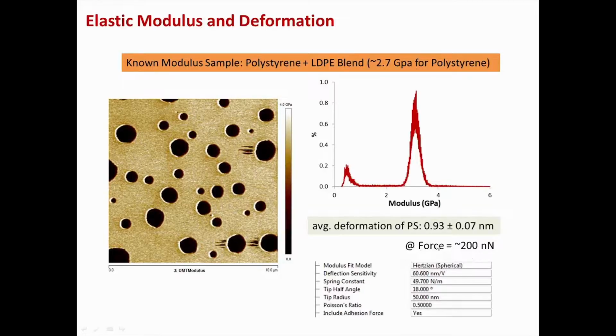Once we did that with a force of almost 200 nanonewton, and indenting it for about 1 nanometer or so, we get this 2.9 to 3 GPa measurement of the polystyrene sample. So we are sure that if we get deformation in this range, our modulus numbers will be around 2.7 GPa. Now if we go back and do the ACI samples measurement, we will have some surety that the measurements are right, or whether something is going wrong.